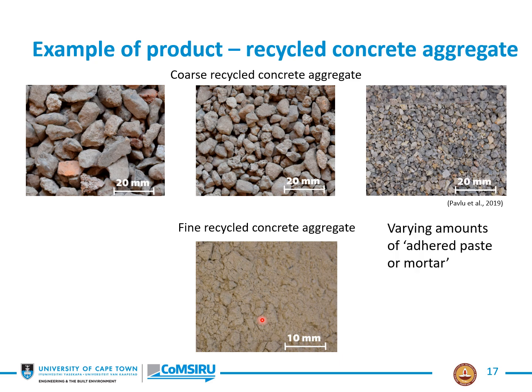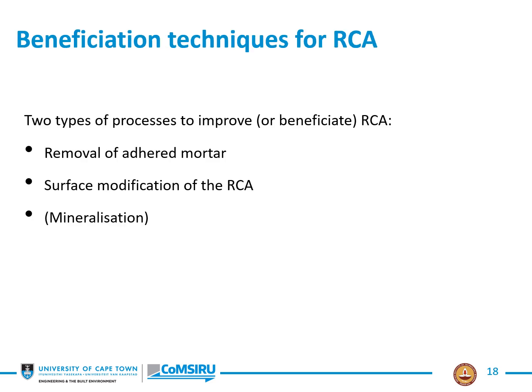And what is common to all of this is what we call the adhered paste or the adhered mortar, and there are varying amounts of this in the recycled material. And this is the issue that we have. And there are 2 processes that we can use to try and improve or beneficiate the recycled concrete aggregates. There's the removal of the adhered mortar, because it is a problem, or there's the surface modification of the recycled concrete aggregates. Thirdly, there's also mineralization, but I won't deal with that in this presentation.